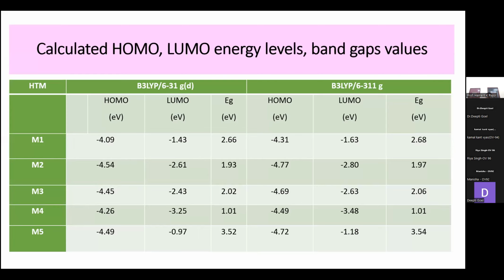Now, about their HOMO-LUMO energy or their band gap. Using two different basis sets, I have calculated the band gap. Now, why two different sets? One set is the more accurate or the more precise one. That is the 6-311 set. That set is more accurate. So for the band gaps calculated for all these, we can see that for 6-31G, all these band gaps are narrower as compared to the other set for which we did the calculation. And some of the materials have experimental values as well, so they were matching as well for M1 and M3.